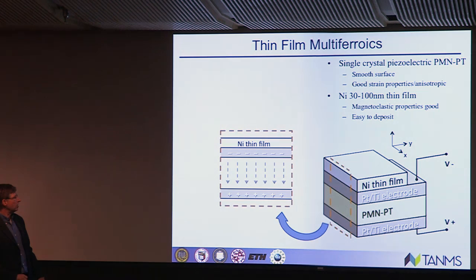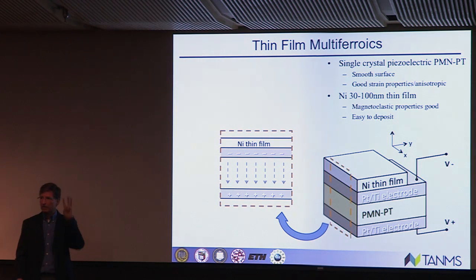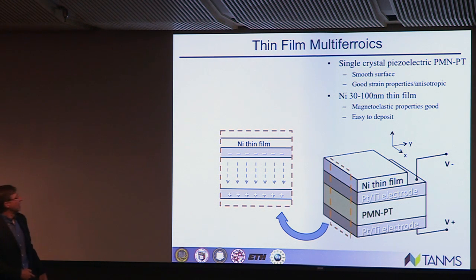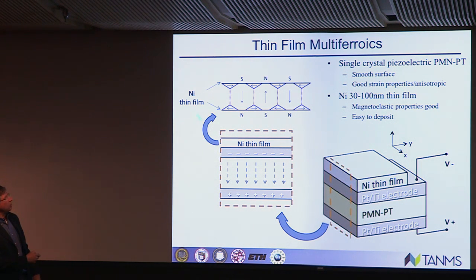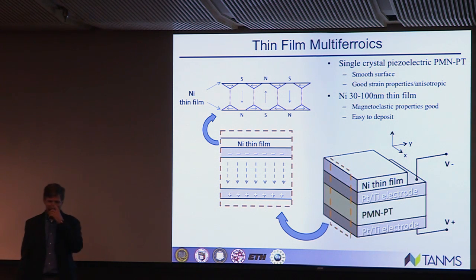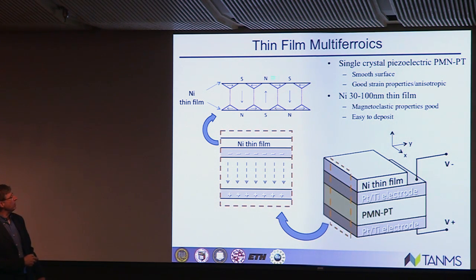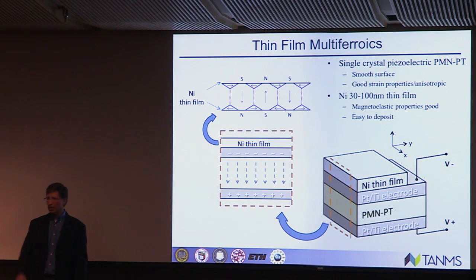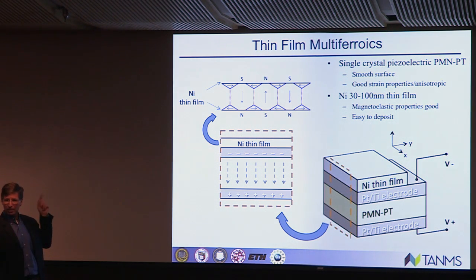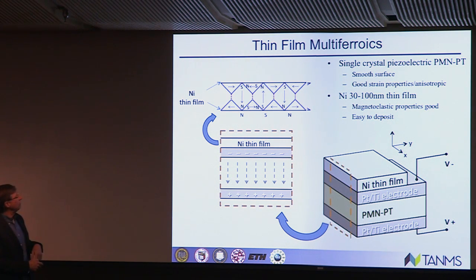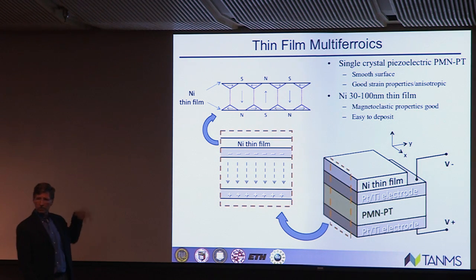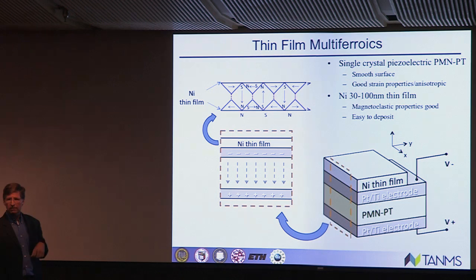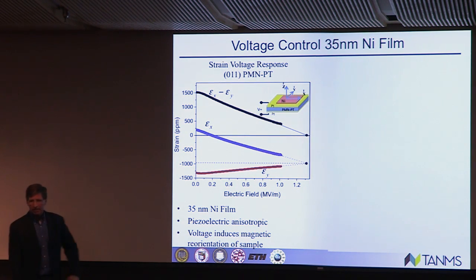So now that we have the structure, what we're going to do is put it together. We're going to apply an electric field, which is going to strain that thin film. And the next 3 slides you're going to see are only based on thin films at different dimensionalities. Now look, if you look at the thin film, what you're going to recognize is that you have domain states in those thin films. Now what's really important, if you look at that top surface, you'll see those north and south poles. So if you're an outside observer, if you get the right type of film, you can actually see that. And what I'm going to try to show you is that we can apply an electric field and actually have those vanish. So once again, we're going to see some thin films where we see outside north and south poles, apply an electric field, and it's going to vanish. So let's go into some data now.